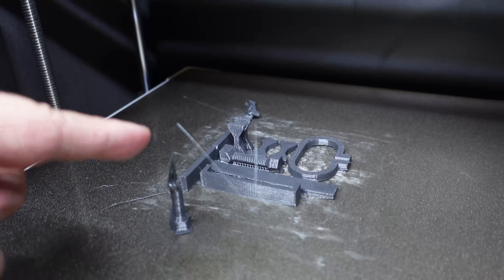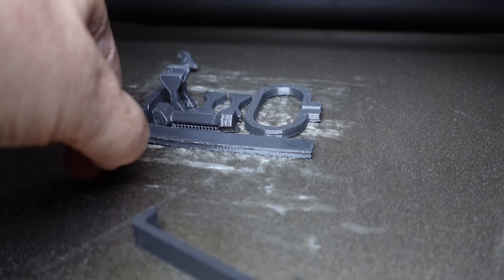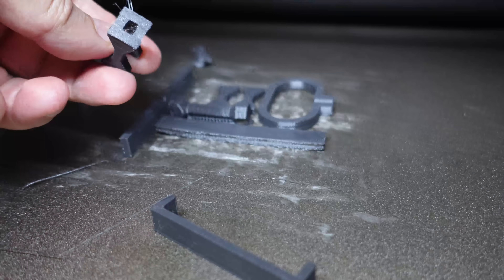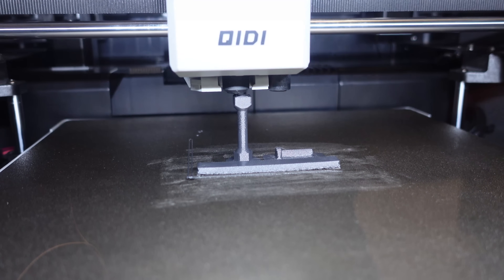This is what I was afraid of — the part cooling was not enough. But where it sticks, the adhesion is quite good. So the warping is the problem. From three failed objects, two are printed, and now the third one.